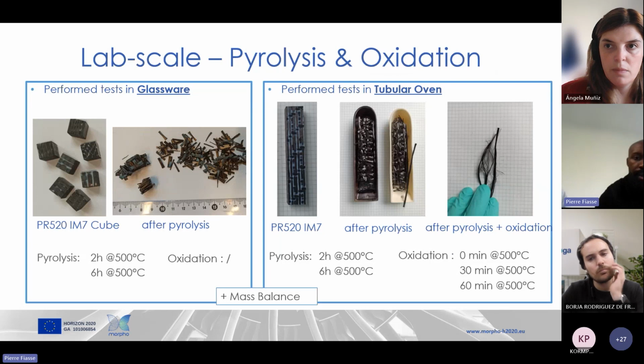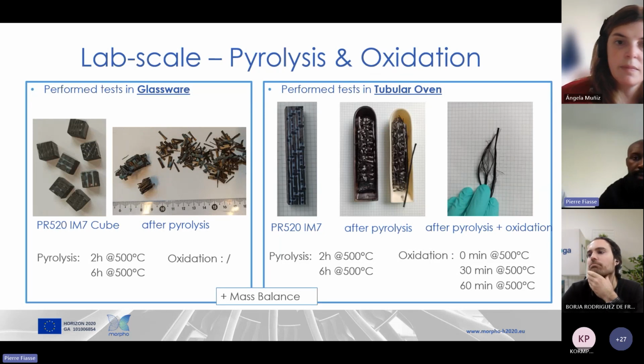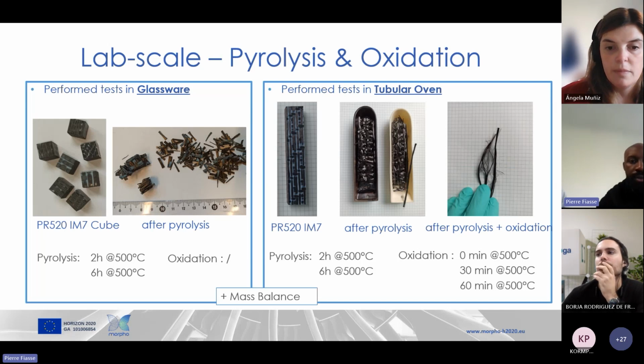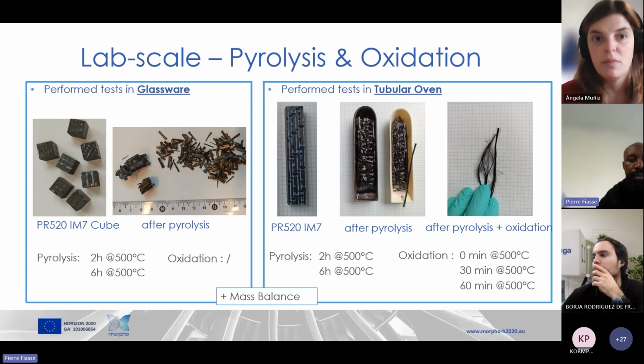Because the recovery of composite was new for us, what we have done is first have a look at what is written in the literature, and we decided to set the limit of our study. We perform tests at always 500 degrees, but we test during 2 hours and 6 hours for the pyrolysis. And then for the oxidation, we try different residence times from 0 minutes to 60 minutes.